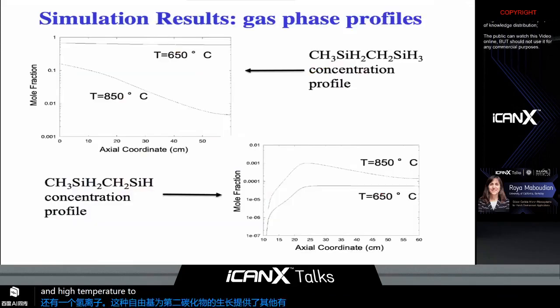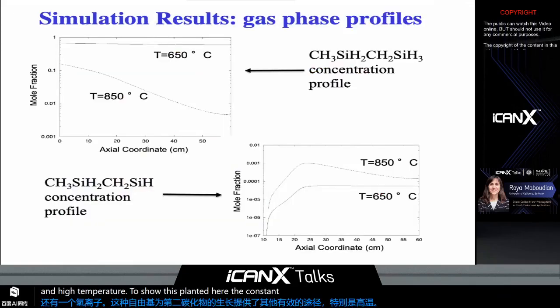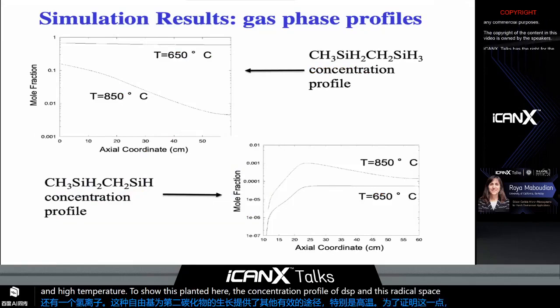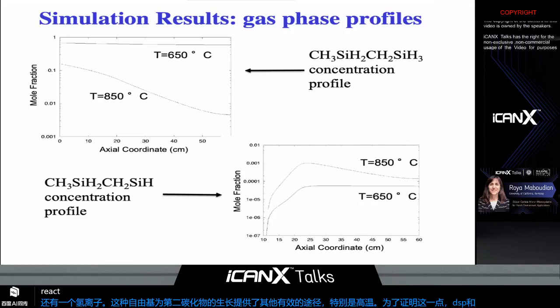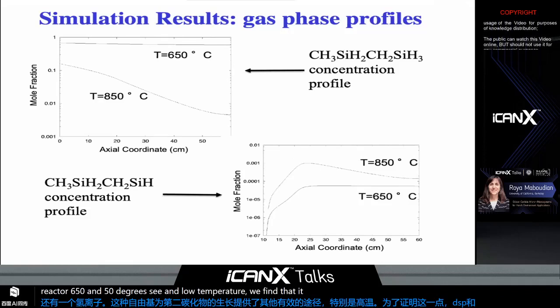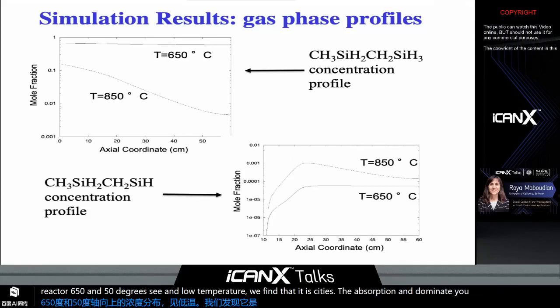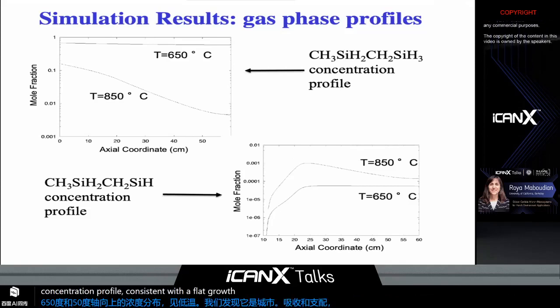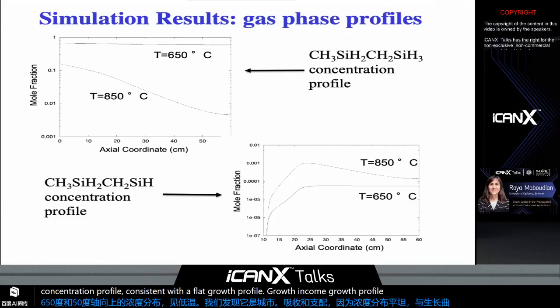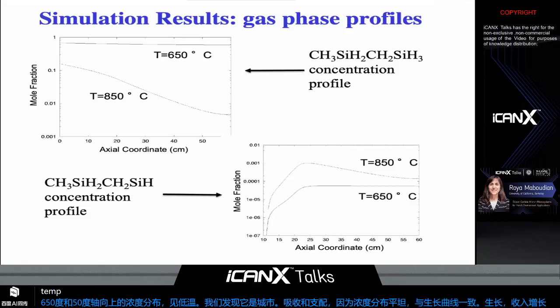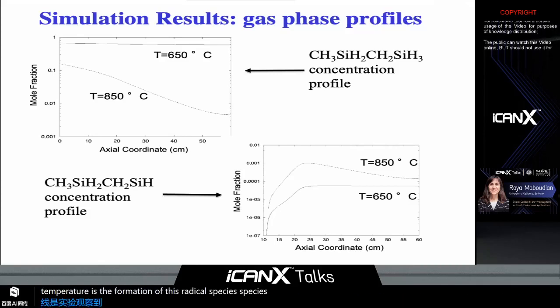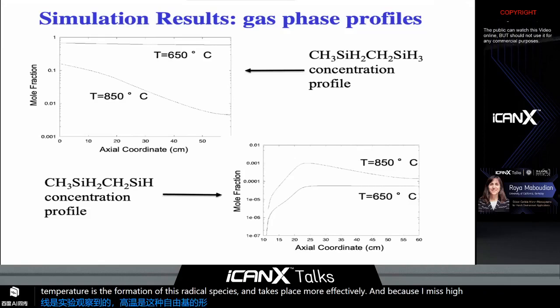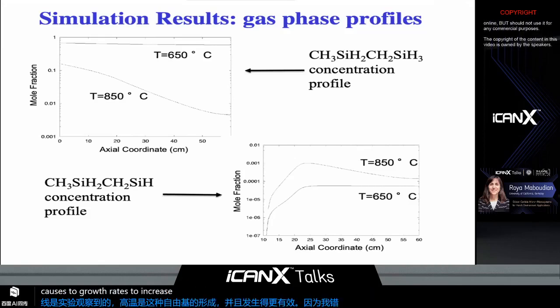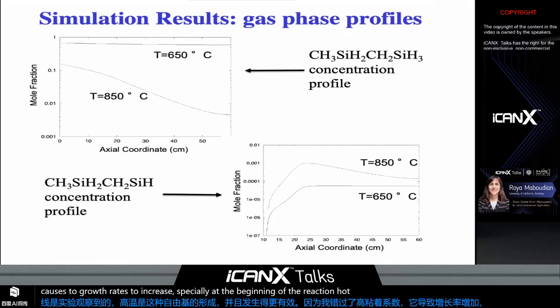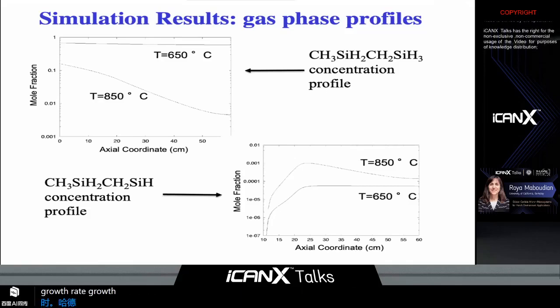To show this, I've plotted here the concentration profile of DSP and this radical species along axial direction in the reactor at 650 and 850 degrees C. At low temperature, we find that it is the DSP adsorption that dominates, with a flat concentration profile consistent with a flat growth profile, thin film growth profile that we observed experimentally. At high temperature, it is the formation of this radical species that takes place more effectively, and because of its high sticking coefficient, it causes the growth rates to increase, especially at the beginning of the reactor hot zone, giving rise to the observed non-uniformity in growth rate at high temperatures.